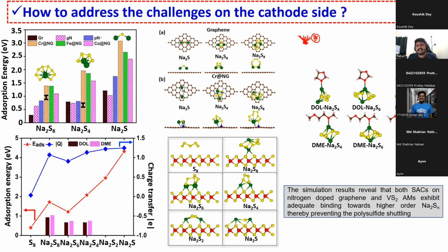In our study, we used chromium, iron, and cobalt-based single atom catalysts for binding the polysulfide as well as converting the polysulfide. This is another work where we used VS2. VS2 is vanadium disulfide, and as you all know, it's conductive in nature. We used these two materials as anchoring materials to see whether they can bind the polysulfides rather than sending them to the electrolyte, whether they can convert the polysulfides, and during the charging process, whether they can break the polysulfide bond and diffuse the sodium ions to the anode itself.